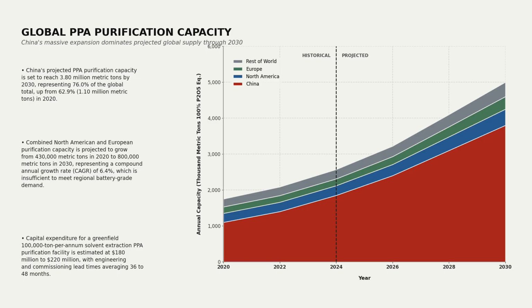The transition to lithium-iron-phosphate battery chemistry has shifted the primary strategic bottleneck of the energy transition. The critical constraint is no longer lithium extraction, but the chemical purification of phosphoric acid. China is projected to control 3.8 million metric tons of purified phosphoric acid capacity by 2030. This represents 76% of the global total, up from 62.9% in 2020.